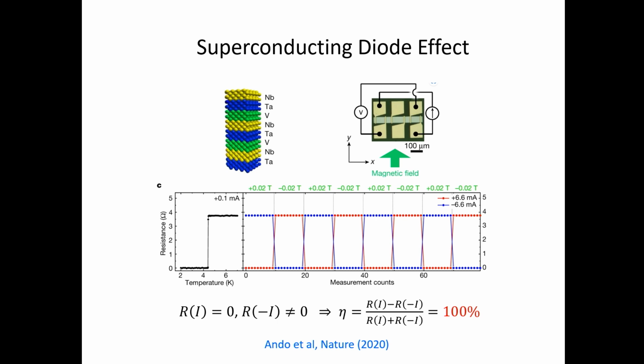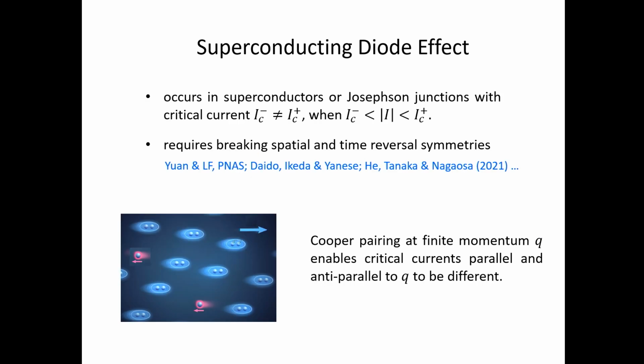Okay, and as a result, for a certain amount of input current, 6.6 milliamp, the system is resistive in one direction, but it's superconducting in the other direction. So in this sense, it's a very large non-reciprocal effect. Resistance goes from zero to non-zero, depending on the direction of current.